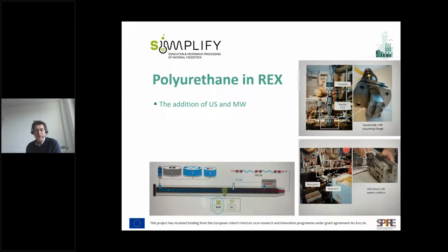and microwave. And also there, based on the more laboratory level work, we're now integrating ultrasound and microwave into the extruder. And you see here a schematic of the extruder. Feed streams are coming in at the left side. Polymerization is happening over the extruder length, and in the end, the formulated polyurethane is collected. And as you can see, microwaves is mostly being applied in the beginning of the system for heating up all the different feed streams. Ultrasound is also being applied, but can be applied along the length of the extruder.